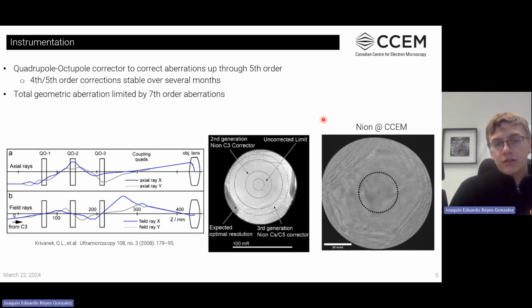For our corrector specifically, if we are using this to do some probe correction at 60 kV, we're able to get a ronchogram that gives us a very wide area that is just flat and aberration free. So we've drawn a little circle here that is approximately where we would insert our aperture. This is where we would actually be collecting data from. And you can see that we actually have a little bit of area outside of there that's still flat and remains aberration free. We still have a bit of area before we become aberration limited. So it's giving us very nice performance at 60 kV.